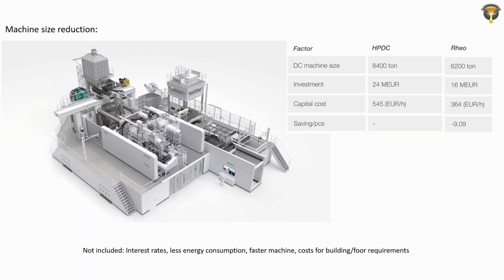You want to have the casting taking up the energy with good properties, and therefore Rheocasting is perfectly suited for that, to get really the long flow lengths. Another thing is that, of course, we can also in that application reduce the machine size, take a bit of the edge off in that investment case. And once we did the calculation, when you go from something like 8,000 ton to 6,000 ton, that makes around €9 per casting. That is nice.